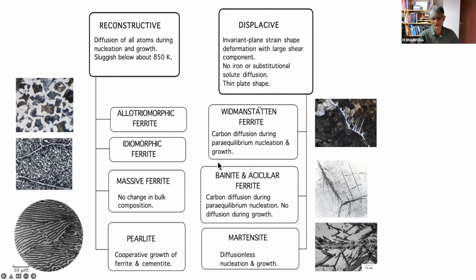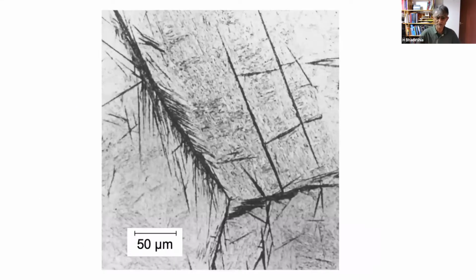And I'm going to focus for the moment on this transformation, which when I started research was incredibly controversial, so much so that if you looked at a textbook, it would have a paragraph on the transformation dismissing it basically as being too hot to handle. Okay, so what does it look like? What does bainite look like in an optical microscope? You see the magnification scale there. This is what appears to be a plate of bainite. It actually is very dark compared with the martensite surrounding it.